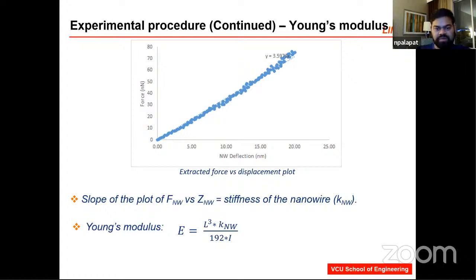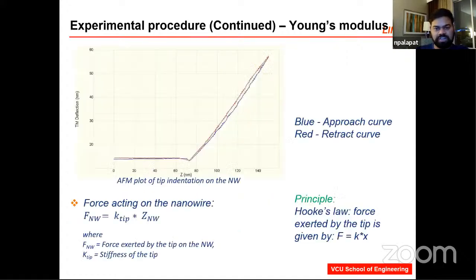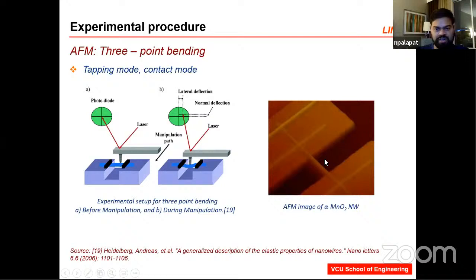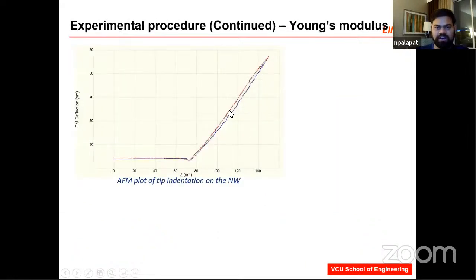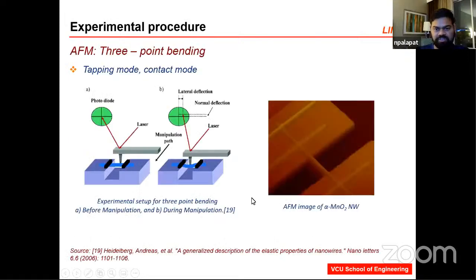So, for example, I talked about using the atomic force tip to press on the nanowire. How do I know that I'm pressing exactly at the center? So you really need to understand how these graphs look like, how the approach and retract curves are tracing each other. That can tell you if you're exactly inserting the force at the center or on the edge, or if it is slipping on the nanowire. That's one thing. The second is nanowires are really small, and for the AFM tip, you have to choose the specific tip that is applicable for your nanowire size and shape of your nanowire or nanomaterial. That's the second judgment that you need to make.